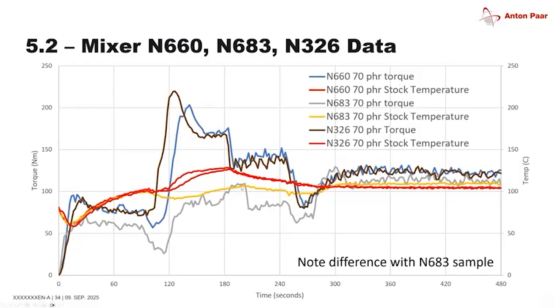This is now a comparison between the three different at 70 PHR. Remember, this was the second part of the test. And this is actually interesting. So we see that the N326, the lowest structured carbon, the hardest, so to speak, and the N660 were similar, but something happened with the N683. There was a change in loading speed because there were issues with actually loading that sample. So you see that gray curve.